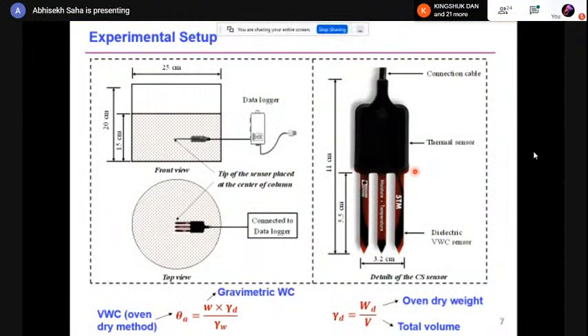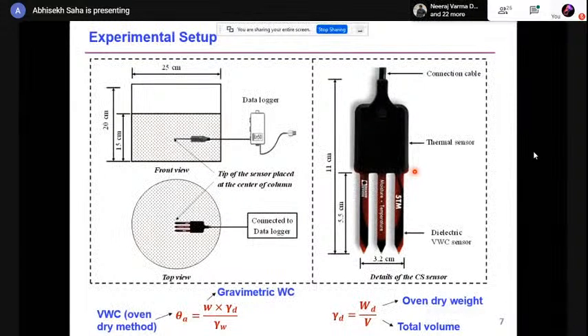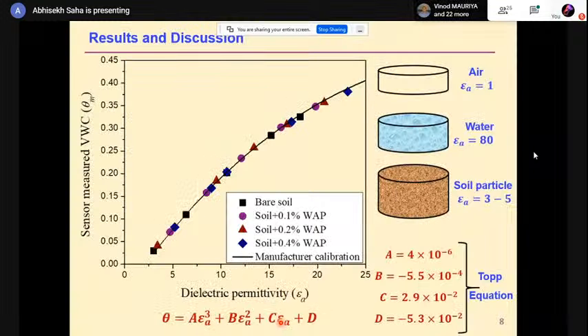Then we have developed this setup. We have taken a PVC column, and we place the bare soil as well as the amended soil at three different concentrations of polymer: 0.1%, 0.2%, and 0.4%. And we measured the water content using the sensors. Then we took out the top soil and extruded the sample, and the volumetric water content was evaluated using the oven dried method. For evaluating the volumetric water content, we measured the gravimetric water content and the dry density of the soil. Now, the measured dielectric permittivity and the sensor measured volumetric water content are presented here.